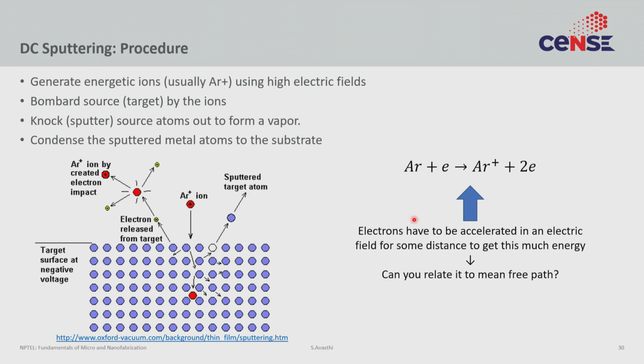Now, if you look at this reaction, what it requires is an energetic electron, like an electron that has been accelerated under electric field for some distance, so it has a lot of energy. Now, you can very easily relate this to the mean free path, right? Because we have looked at that under high vacuum and under low vacuum, what is the mean free path? So the maximum energy that the electron or argon plus ion can actually attain within this electric field is limited by the mean free path.